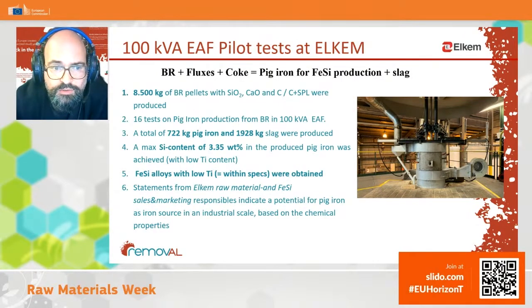They tested more than 8 tons of bauxite residue, producing some 700 kilograms of pig iron and 2,000 kilograms of slag. And they got a pig iron that has 3.3% silicon inside, so it's a good raw material for them to produce then ferrosilicon alloys, and in fact it's within specs and could be used commercially.